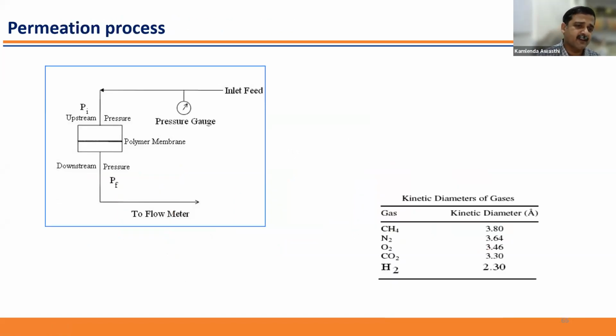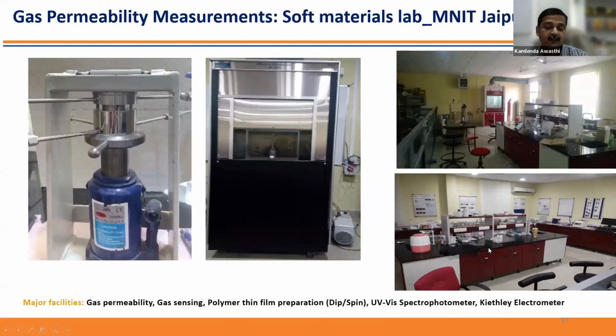This is a schematic diagram for any gas permeability or gas separation setup. Here we use this polymer membrane, and here we apply higher pressure. This is the downstream pressure coming to the flow meter, and this way we can calculate the flux coming out of the membrane. And again, please remember the kinetic diameter, written here in angstroms. You can see that apart from hydrogen, these are very close to each other, so how can we separate them? And these are the gas permeability setups available in our lab here at MNIT Jaipur: a diffusion permeator for dense membranes, and a self-developed setup for porous membranes.